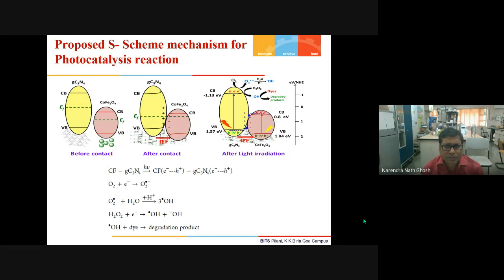It has their own conduction band and valence band. For graphitic carbon nitride, the conduction band is minus 1.13 electron volt and the valence band is 1.57 electron volt. Whereas for the cobalt ferrite, the conduction band is 0.8 and the valence band is 1.84 volt. When these two semiconductors come in contact, they form an electrically charged layer at their contact point. Like the graphitic carbon nitride side, there is a positive layer, and the cobalt ferrite side, it's a negative layer.